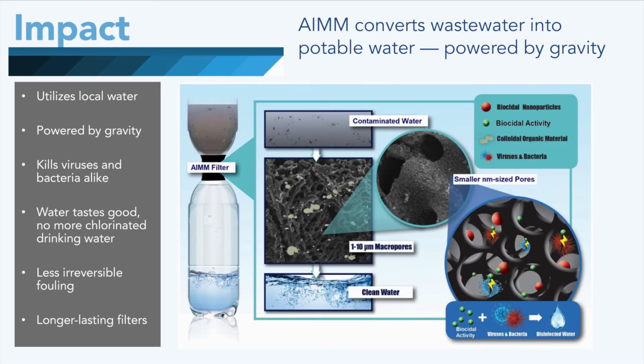At AIMM, in order to address these issues, we have created a water filter technology that will take contaminated water and turn it into clean, good-tasting drinking water. The way this is done is by using a filter that is made up predominantly of a porous carbon material that has multiple levels of porosity. There are relatively large micron-scale pores that capture the larger organic materials present in the turbid water, that then have smaller nanometer-sized pores within the larger pore walls that capture smaller viruses and bacteria.